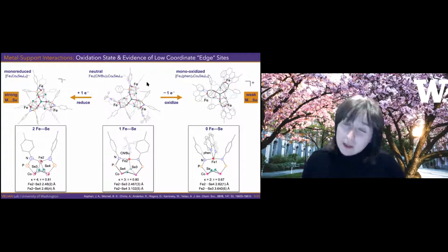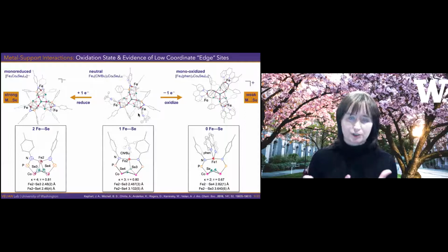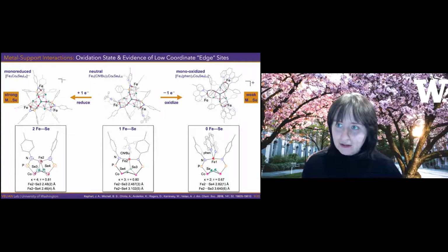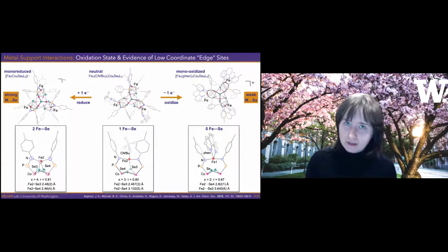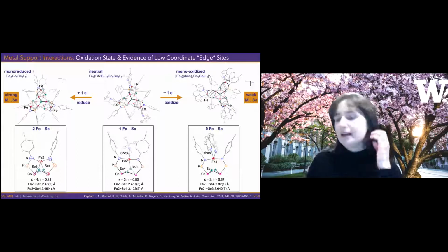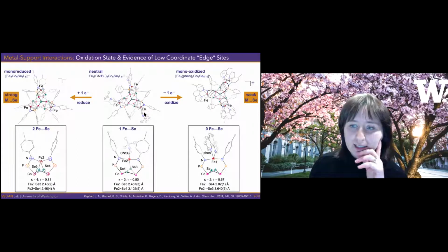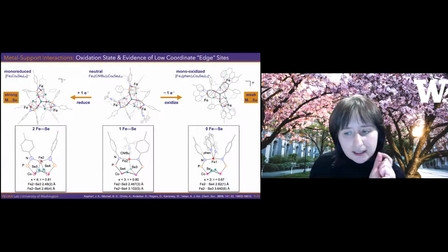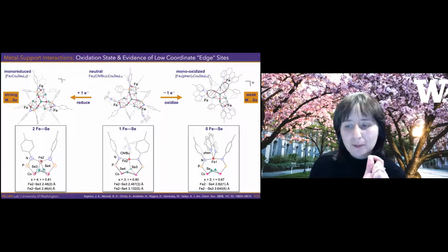Now, what was really cool to see is that if we take this cluster and then we oxidize it, the way the metal, the edge site, engages with the cluster support changes. And it doesn't just change because we introduced a chelating ligand. This is a phenanthroline, so you would expect it to interact stronger with the iron and perhaps pull it out of that pocket. But that's true also for other ligands, including monodentate ones: upon oxidation you alter dramatically the interaction between the iron and the selenium. So you no longer have a bonding interaction between the iron and selenium upon oxidation.